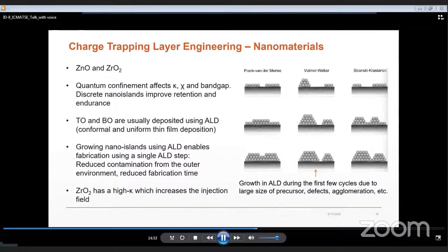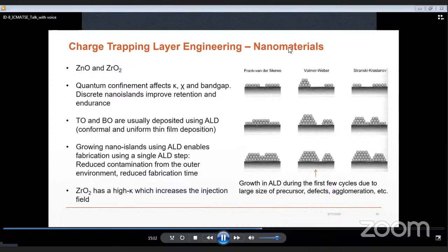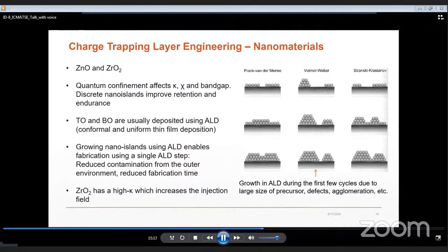So the reason for using nanomaterials is the possibility to tune the electronic properties based on quantum confinement effects, such that we can increase their band gap in addition to increasing their charge trapping density and thus lower the needed program and erase voltage. In addition, since the blocking oxides of the memory are usually grown using the ALD tool, being able to deposit the charge trapping layer using the same tool would reduce the time needed for fabrication. In addition, doing the deposition in a single ALD step without taking the sample out of the tool would reduce the potential contamination from the outer environment.